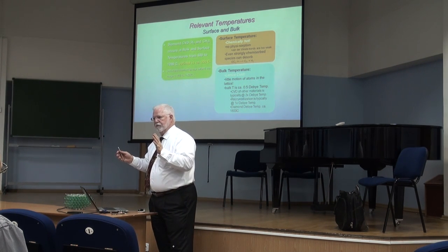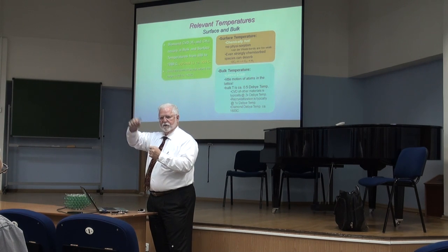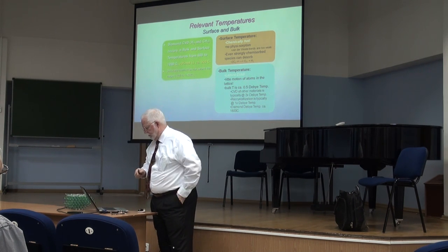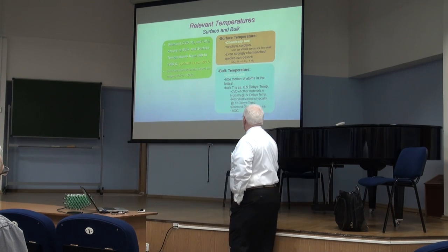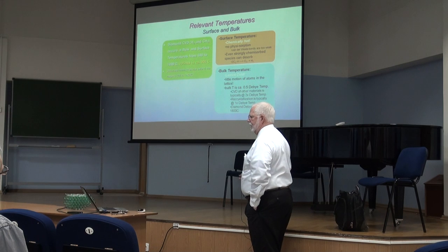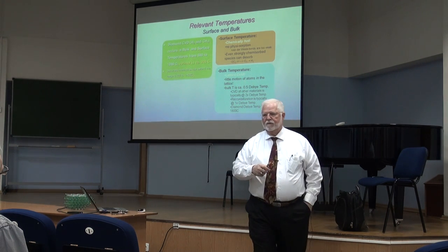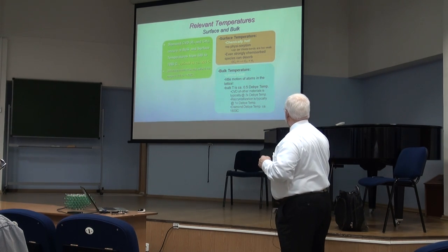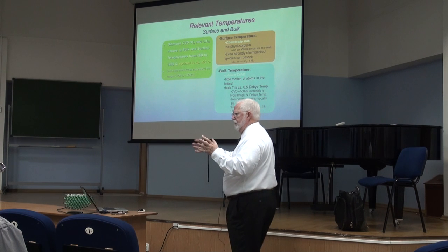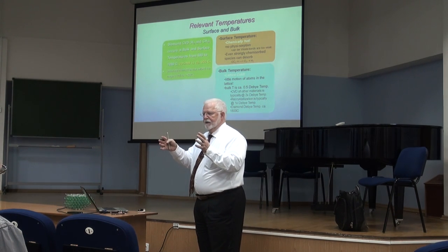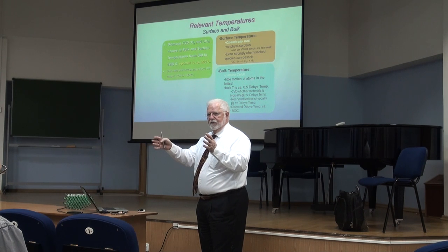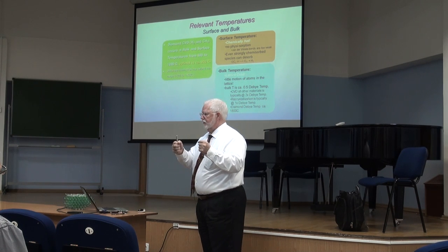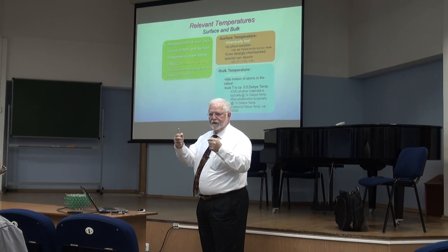So, in the growth of diamond, we're really only going to address the chemistry that occurs at individual C-H bonds for today's talk. The other point I would like to make is diamond has the highest Debye temperature of any material. The Debye temperature is a reflection of thermal motion in the lattice. And we're growing diamond at half its Debye temperature. That means there's very little thermal motion in this lattice. So very few things can actually diffuse in the lattice. Atoms cannot rearrange themselves very well under these conditions. So that means if I grow a defect into diamond, I can't anneal it out. It just stays there. It's locked.